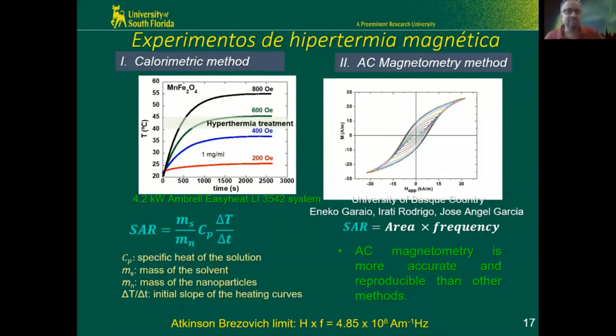You cannot arbitrarily apply very large fields and very high frequency, because you will cause nervous stimulation. You'll have paralytic attacks, okay? The nervous system will be in trouble. So one has to be very careful, and this is why for the magnetic hyperthermia community, you have to work with these fields, these limits. The limit here is the product of the field and the frequency, and in SI units, it's that. Think of it as some kind of a pain threshold, okay?